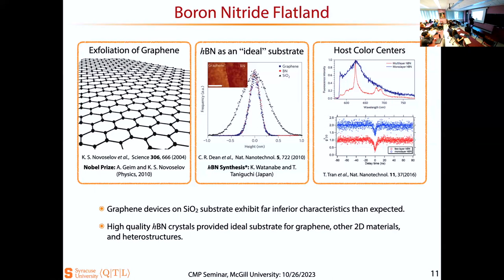Even now, when I work with TMDC materials, I always either encapsulate them or use hBN as a substrate. But then in 2016, a paper came out showing that boron nitride is an insulator with a band gap of about 6 eV. So it's a wide band gap insulator, and there is a very good chance that there must be some mid-gap states which can act as single photon sources. And this is what they showed. Yes, indeed, there are defects that are single photon sources. So that's how I see it: graphene, substrate, and then it also has a quantum property. It can not only be used as a substrate, but also has a quantum property as well. So this is how I see the research on how boron nitride entered the 2D field.